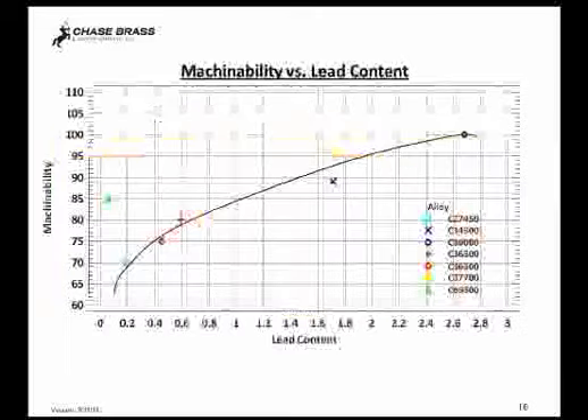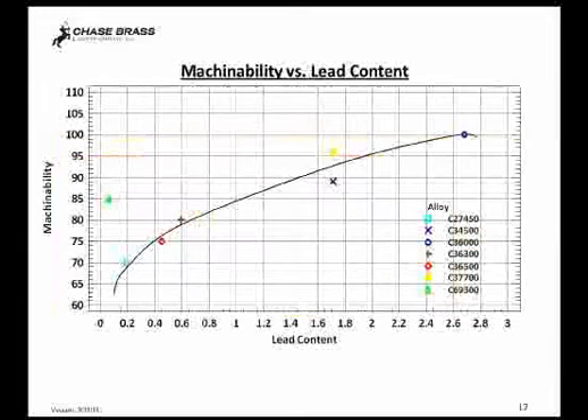lead to see. And where in alloy 360 the lead particles break up the chips during machining, in alloy 693 and other lead-free alloys, there's something else in there to break up the chips. In this particular case, you have the lighter colored kappa and gamma phase that help break up the chips. There's other alloys that might contain bismuth or tellurium, and those would be present as discrete particles in the matrix and break up the chips for those particular alloys.